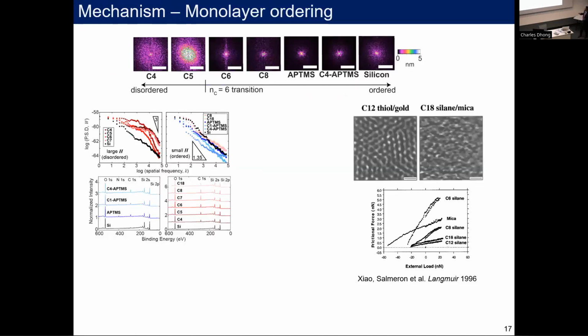And so really we don't have individual receptors on our skin like the way you have for smell or touch that can recognize chemical functionalities. So really what's happening here is that if you have a long enough chain length or enough intermolecular forces, basically it goes from a liquid-like surface to a more solid-like surface. And so people have known this from AFM that you will have much higher friction at lower chain lengths. And this has been shown through AFM, which is exactly kind of what we see.